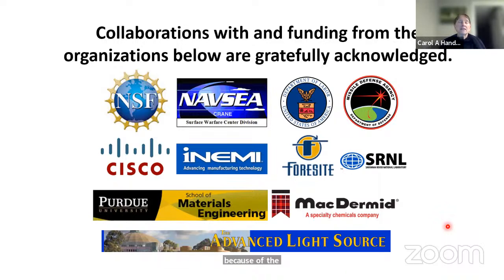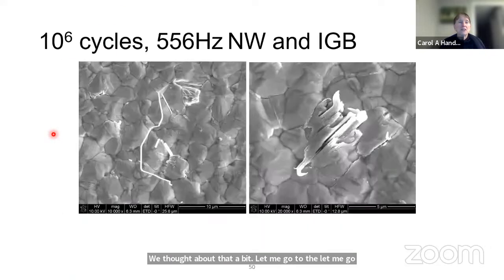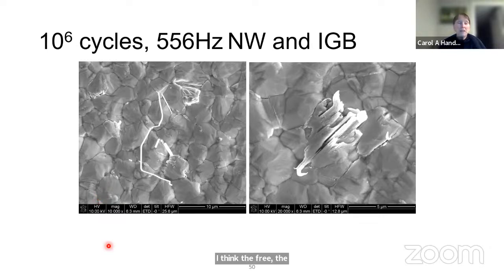So I think it doesn't matter so much. Yeah, that's a really interesting question. We've thought about that a bit. Let me go to one of the earlier images. And actually, I think this one will do. I think the surfaces are actually pinned because there are grain boundary grooves in the oxide. So having the grain boundary grooves there in the oxide actually stabilizes the surfaces. And so I think that's one of the reasons why, yeah, surface energy doesn't play a significant role as far as I know.